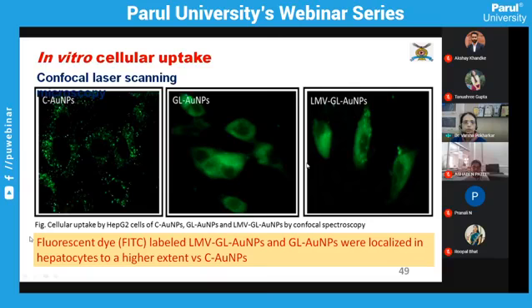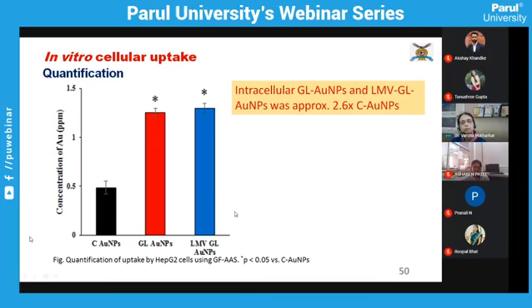So you can see just from the intensity that whereas for the citrate reduced gold nanoparticles the fluorescence intensity was quite less, compared to the glycyrrhizin capped gold nanoparticles, considerable fluorescent intensity indicated that these FITC labeled lamivudine gold nanoparticles and the glycyrrhizin gold nanoparticles were localized in the hepatocytes to a very high extent as compared to the citrate reduced gold nanoparticle. So our objective or strategy, that we can use glycyrrhizin as a targeting ligand successfully for hepatocyte targeting, was established.